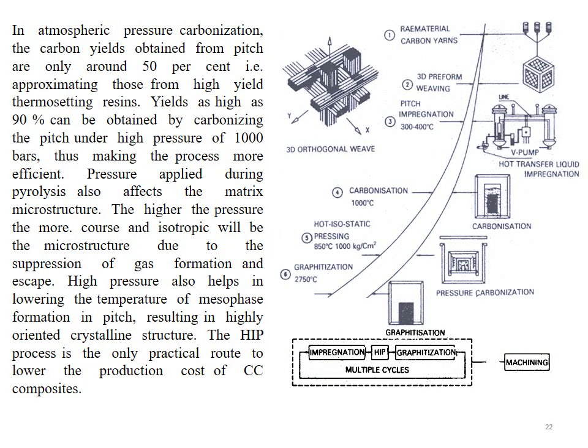In atmospheric pressure carbonization, the carbon yields obtained from pitch are only around 50%. That's approximating those from high yield thermosetting resins. Yields as high as 90% can be obtained by carbonizing the pitch under high pressure of 1000 bars, thus making the process more efficient. Pressure applied during the pyrolysis also affects the matrix microstructure.